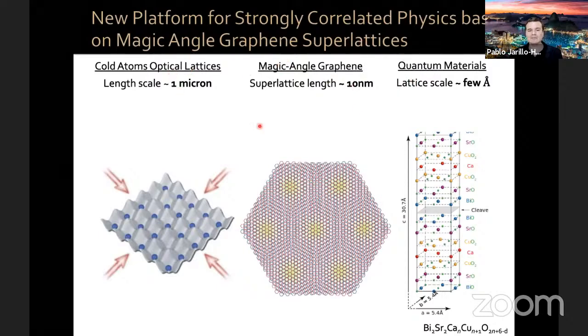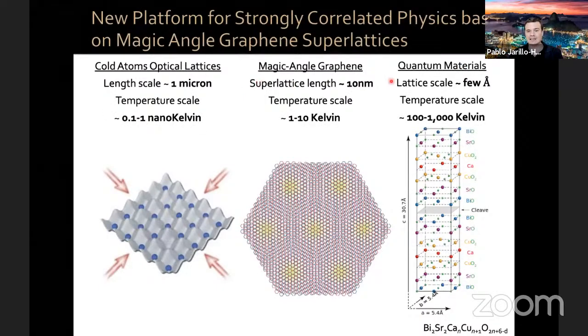So in that sense, magic angle graphene and other Moiré superlattices constitute a very complementary platform to investigate strongly correlated systems. Associated with these length scales, you have energy scales. In typical quantum materials, the energy or temperature scale is of the order of 100 to 1000 Kelvin. In ultra-cold atoms, you have about 0.1 to 1 nanokelvin. Because in magic angle graphene this length scale is intermediate, you also have an intermediate temperature scale, which is of the order of 1 to 10 Kelvin, as I will show later.